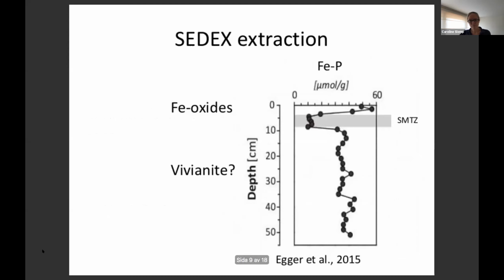Next slide, please. And so what we did first was see, okay, if we use that SEDEX extraction, do we find iron-bound phosphorus? Well, we did, and we saw a lot of it. And you can see that here, those high concentrations below that shaded area, that's where we see iron-bound phosphorus. But what fraction now is Vivianite?